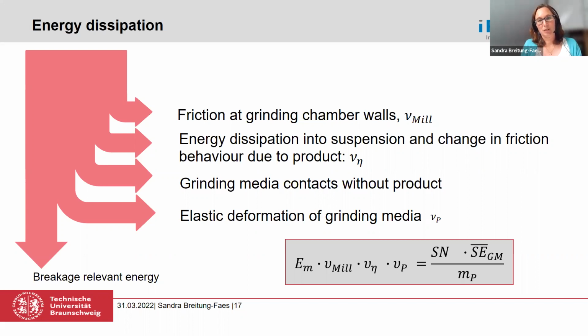Then there was the idea of grinding media contacts without product, but I think we can neglect it because for fine products and higher concentrations, we see that you always have product in between, and the deformation behavior, and at least you came up with this. These two, the energy transfer coefficients of the suspension and the product, were already included or neglected. And before I tell you something about the energy transfer coefficient of the mill, I would like to first talk about the stress number itself. Because in the first part, where we predicted optimum process parameters, we had the main view on the stress energy. And when we want to come up with the grinding time or the energy, we also need an idea how to find the stress number for it.